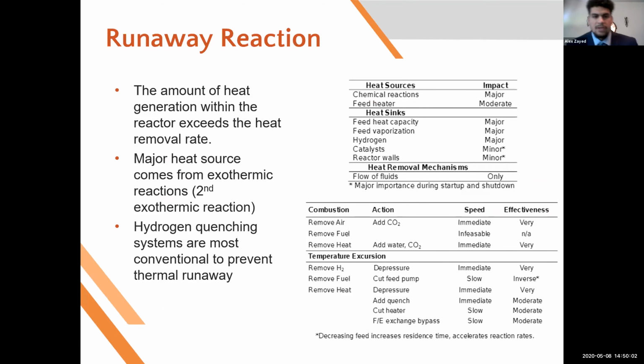Okay, so one of the major safety aspects that we considered in this project is obviously thermal runaway. As we researched runaway reactions, we found the main heat sources, as you can see in that table, and heat sinks, as well as different removal mechanisms and how effective they are. On the bottom chart, they list many temperature excursion methods. One is to depressurize the reactor, which is very effective, but we found that would definitely give us worse product yield. So we determined the best way to prevent thermal runaway was a hydrogen quench system.